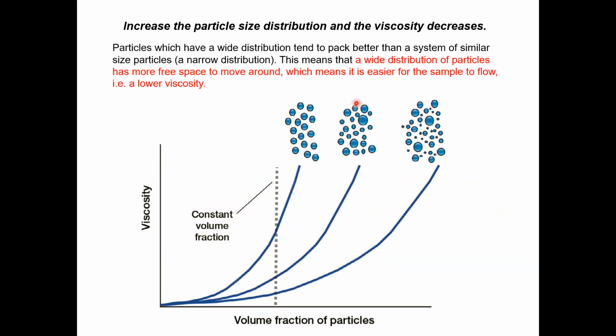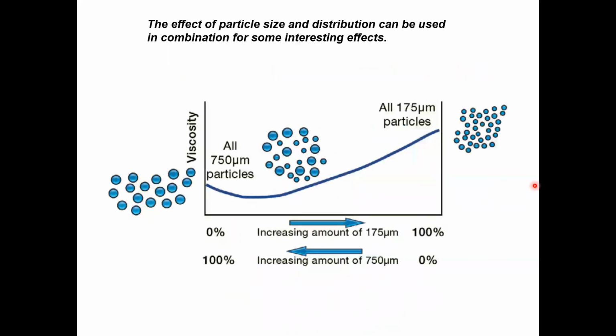Or you can control the particle size. So if you use mono-sized particles, as opposed to mixed particles, 2 different sizes, 3 different sizes, you can see that viscosity keeps on decreasing for a certain volume fraction of the particle. Monosize will give you higher viscosity, compared to multi-size, lower and lower viscosity, because you get easier flow with a large range of particle size. So you can actually use the optimum mixture.